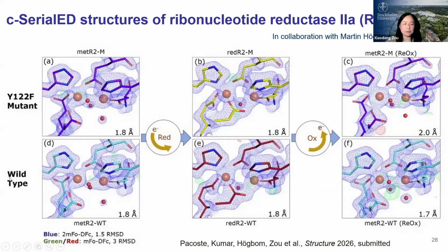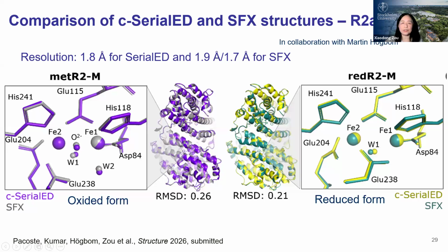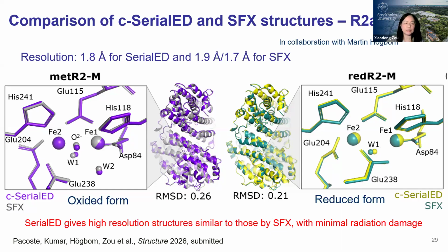So this is the mutant type and this is the wild type. They are all closely related. And interestingly, we can look at our structure obtained by c-SerialED and also the structure obtained from the X-ray free electron laser, SFX. You see that the structures, both the oxidized form and the reduced form, are very close. These two structures have an RMSD, as you see here, of 0.26 and 0.21 angstrom. This means that we can really use electron diffraction to study the structure and get very good results, as good as XFEL, which is very rare.